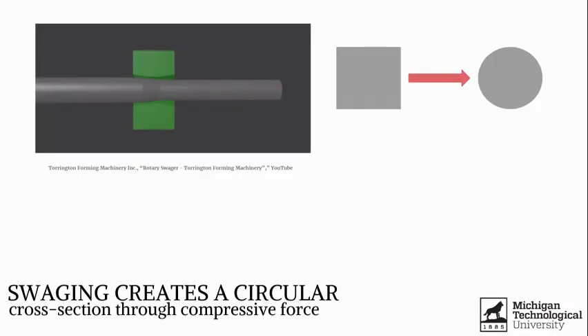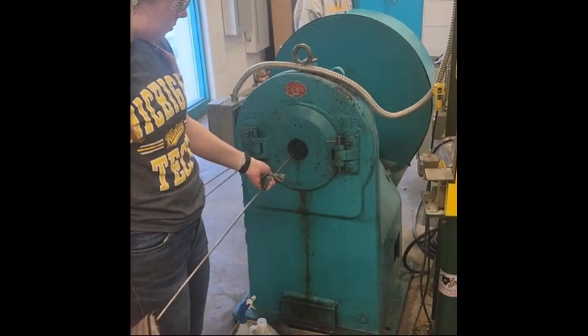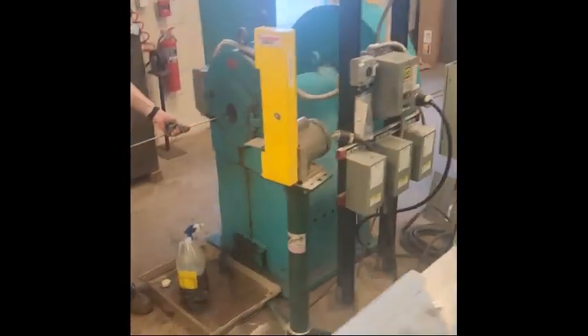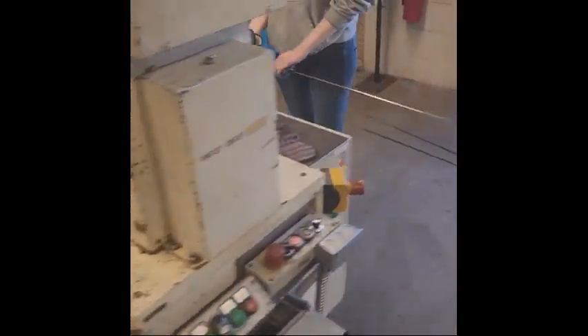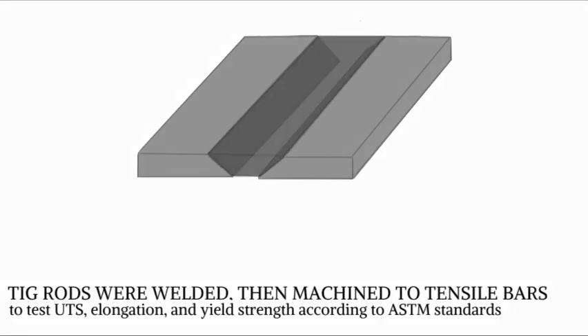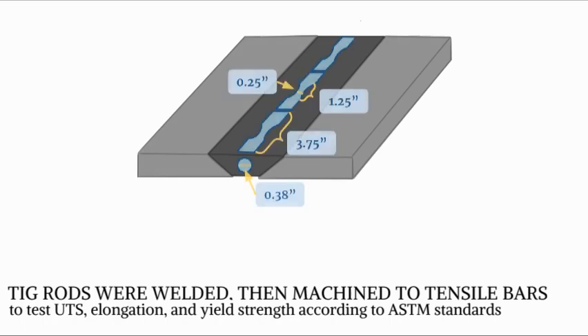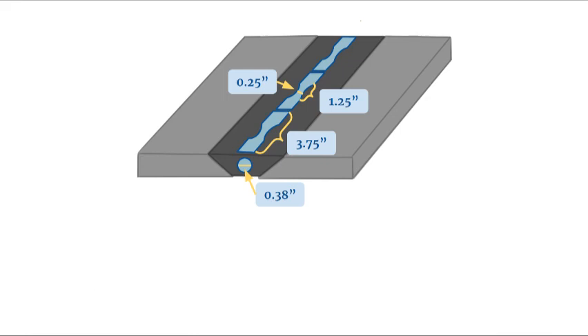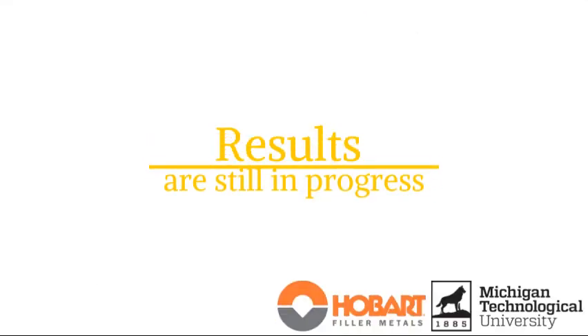Like rod rolling, swaging also uses compressive force to reduce the cross-sectional area of a sample, but instead of rollers, it uses dies that open and close around the sample, resulting in a round cross-sectional area. Our bars were swaged down to a 1/4 inch diameter rod before some samples were shipped to our sponsor. The kept bars were further swaged to a 1/8 inch diameter. The 1/8 inch wire was welded into a V-notch between 2 steel plates and then machined into round tensile bars to test the elongation, ultimate tensile strength, and yield strength of our alloys. At this time, we are still waiting on the results of our project to determine which alloy will perform the best.